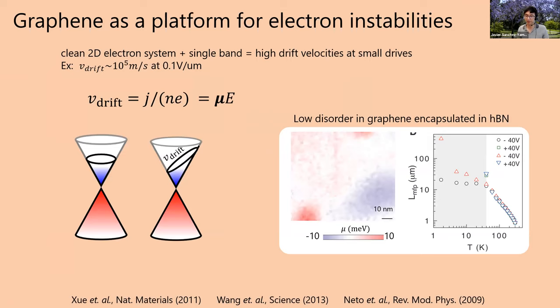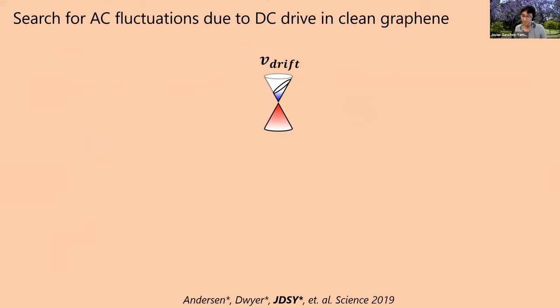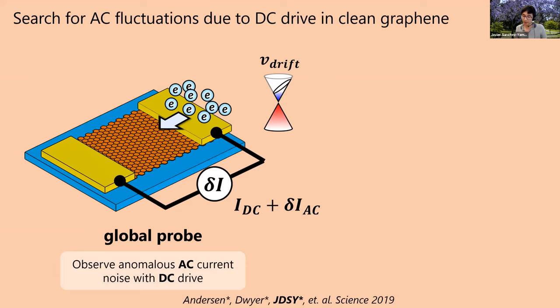Let me just briefly say that graphene is a good system for doing these types of studies because it's very clean. That means that if you apply a small electric field, the average velocity of the electrons can be really, really high, as large as 10 to the 5 meters per second at a pretty small electric field. That will tilt the Fermi surface of the electrons so that it's very strongly out of equilibrium, and you can maybe get some interesting things to happen. Okay, so that's the experiment.